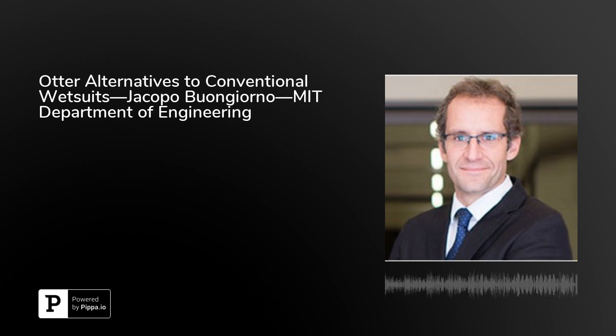Sure. So, in fact, it's interesting. In some extreme cases, we can get an effective thermal conductivity of the treated neoprene which is equivalent to the thermal conductivity of air. So it's almost like you're wearing a garment made of air, right? So it's an interesting way to look at it. It's not really made of air. It's made of a composite material that has a thermal conductivity of air. So very, very low, that is.